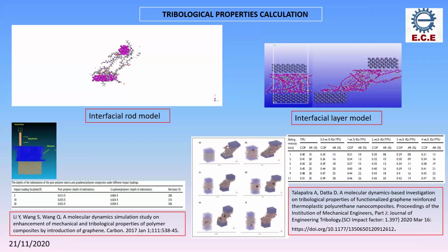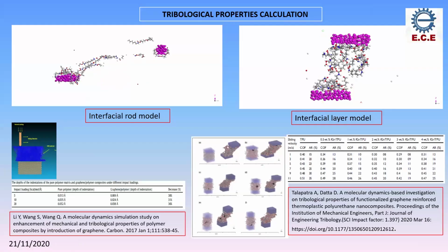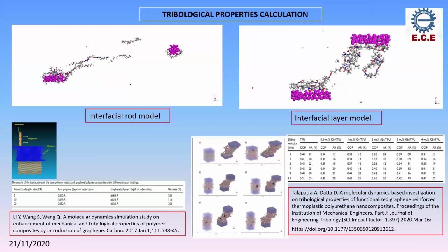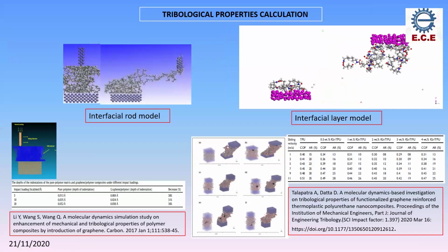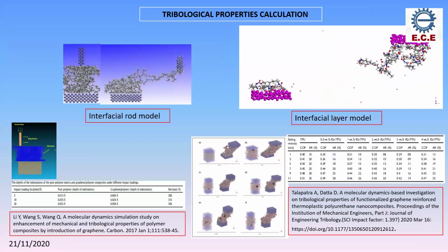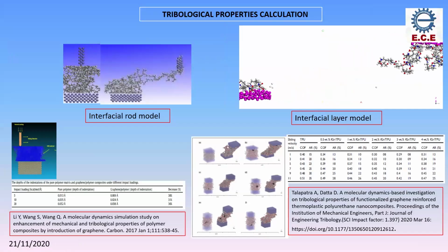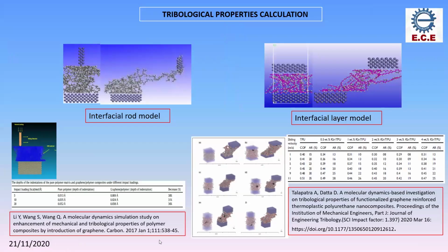So there will be two simulations, the interfacial model and the layer model. For the interfacial models, we have to see the rod and layer model, a tool for simulations with the different properties of the nanocomposite, coefficient of friction as well as the abrasion rate. And in this study, we see that after 3% the property decreases due to the agglomeration of the graphene.